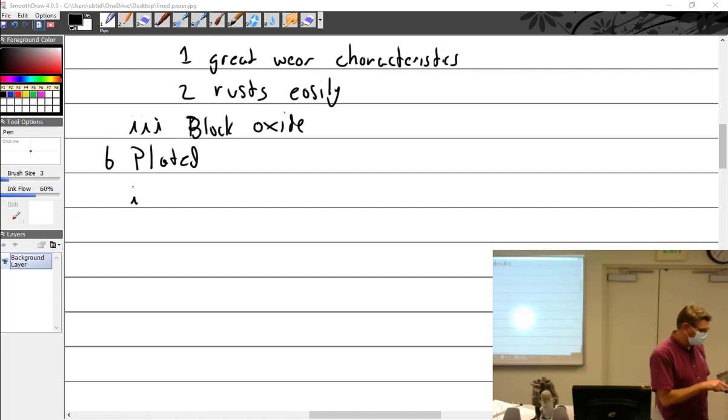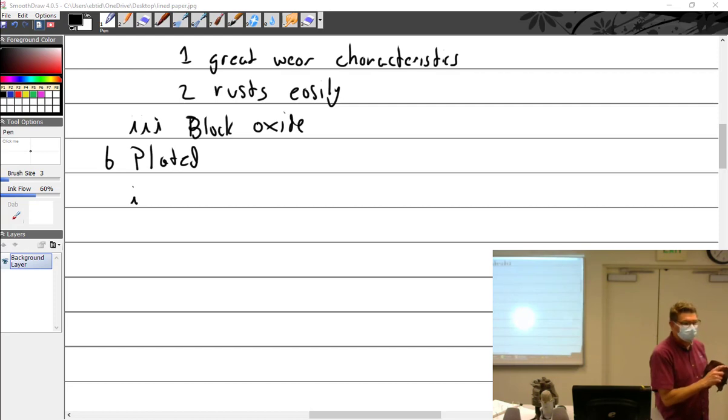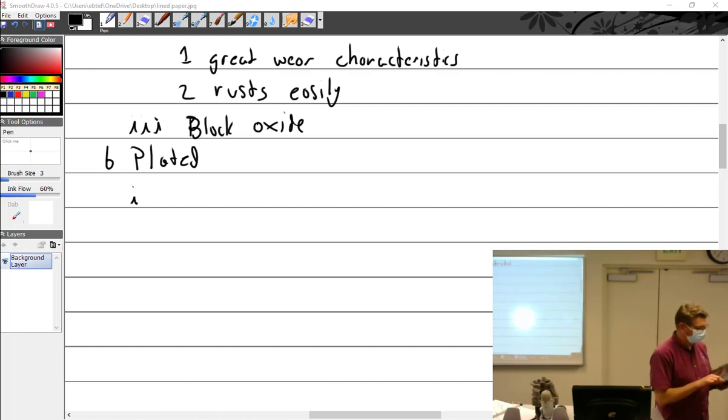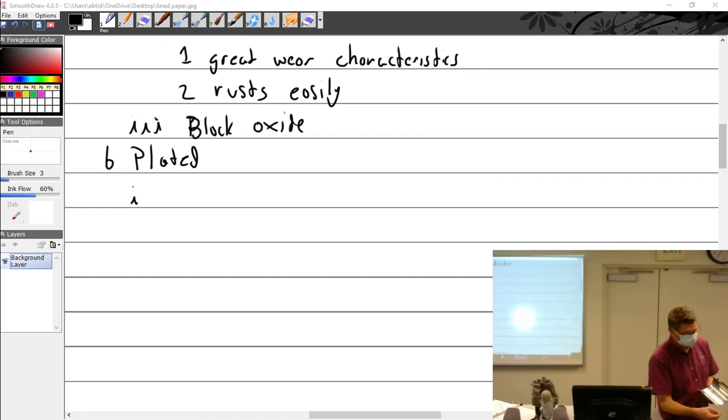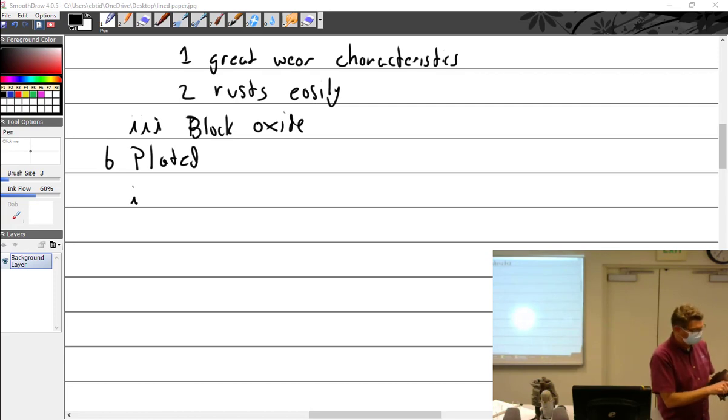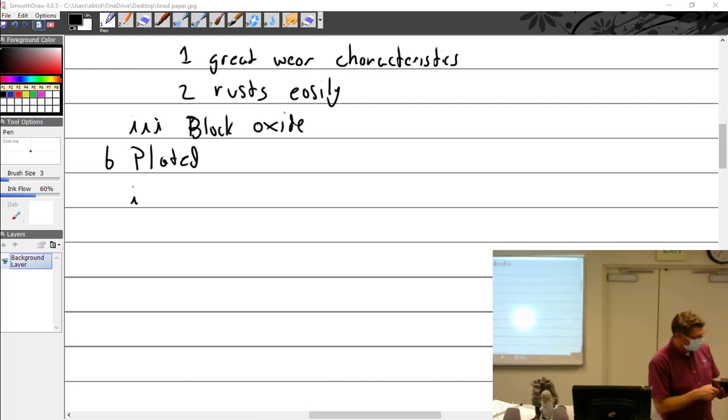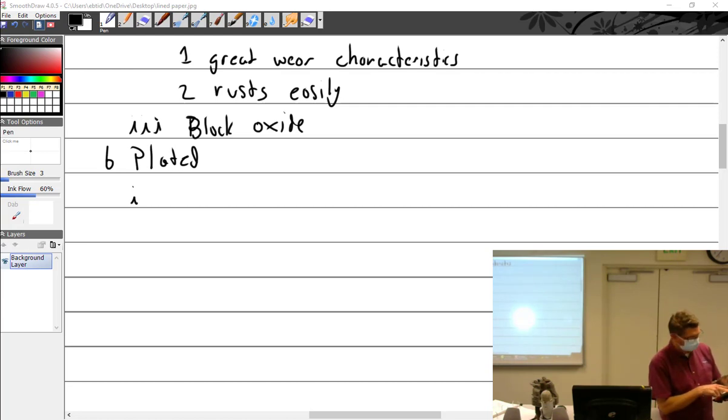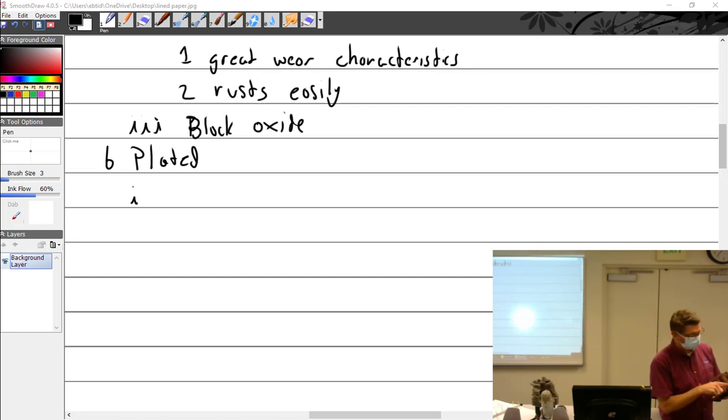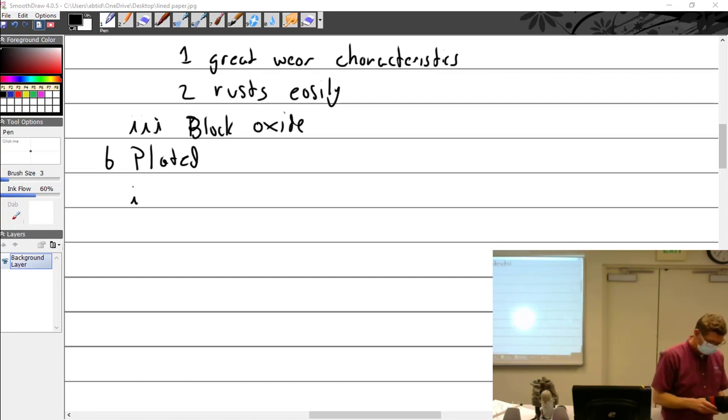You see all the channel chrome in it. At this end where the threads are you can see how badly it's worn where the ring would have went up there. The channeling is kind of worn away about an inch down. When the channeling wears away it becomes very slick and then the oil gets by.